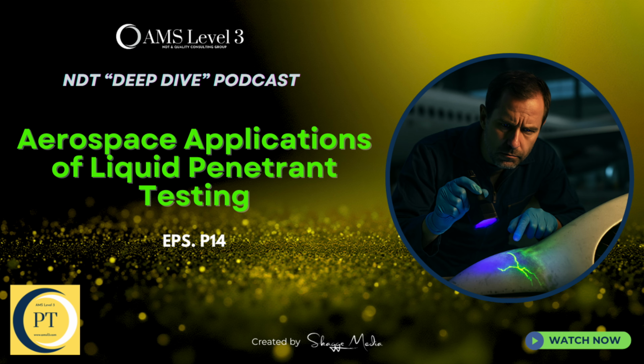And this isn't just bureaucratic nitpicking. It's a vital chemical control point. So what's the risk you're trying to prevent with only using QPL materials? What could go wrong? The primary risk, especially with the high-temperature alloys you see in turbines, is corrosion and material degradation. We are specifically trying to control contaminants, like high sulfur or high chlorine content. If a penetrant or developer has too much of that stuff, and the part is, say, a nickel-based superalloy operating under intense heat, that chemical residue can lead to catastrophic stress corrosion cracking later in service. Wow. So the QPL guarantees that the product's formulation has been chemically verified not to poison the flight material.